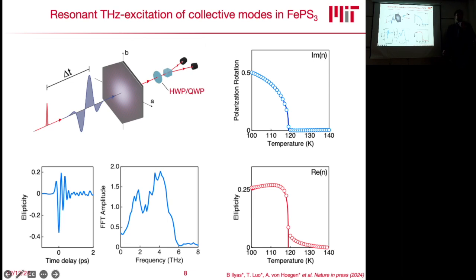And number 3 is we need the excitation. This is something that I've helped pioneer in my old group, and this is also something that Gedik's group started working on already before I came, but then I also jumped on board, where we use strong terahertz fields with field strength of the order of 1 megavolt per centimeter. So this is already a pretty large fraction of interatomic fields. These are very, very large terahertz transients.